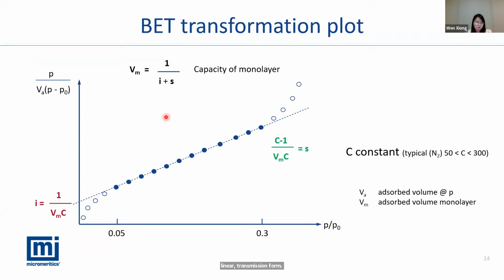This graph is the corresponding data, which we call the BET transform plot. It is important to note that the linear form does not apply to the whole range. For example, here, when the relative pressure is lower than 0.05, it doesn't fit the linear form. For non-porous, mesoporous or macroporous materials, this range is typically between relative pressure 0.05 to 0.3, which is a very typical BET range.